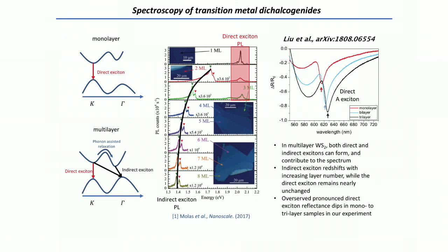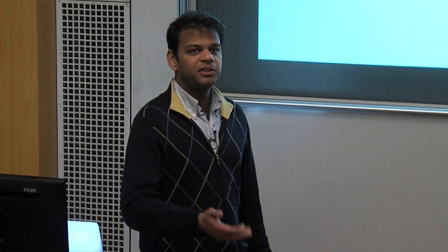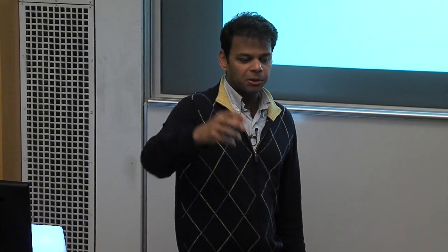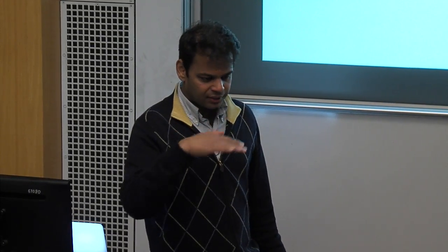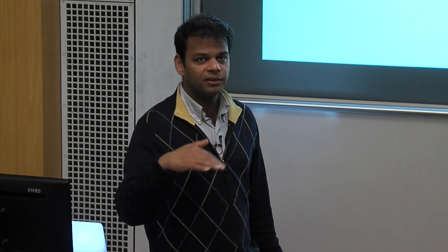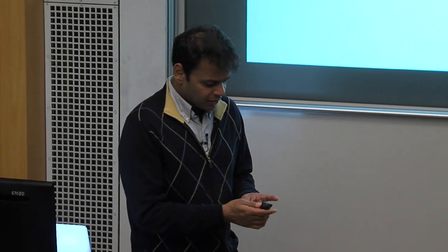But another very interesting aspect is what I'm going to talk about now. Just to take you a few steps back, the question we started to ask was, what if we start to increase the number of excitons in the system systematically? Which basically means, what if we stack more layers, going from monolayer to bilayer to a trilayer and beyond? The distance between the layers is very, very small, and the plasmonic length scale is of the order of, let's say, 10 nanometers. So within 10 nanometers, we can stack many layers, which basically means we can increase the exciton density in the vicinity of the field. So what will happen?